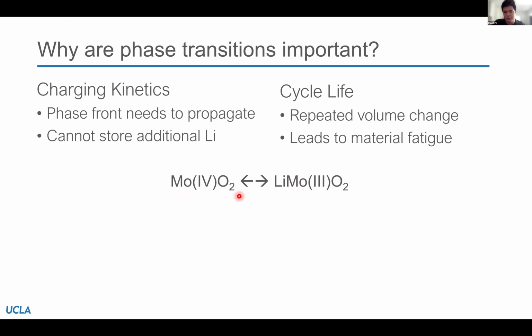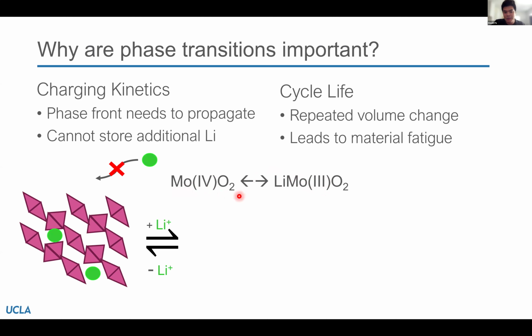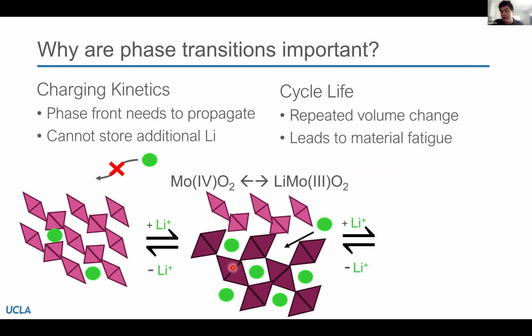If we look at this at a structural level, we have exactly that, empty MoO2, where we insert lithium. But now talking about phase transitions, at a certain point, you could think of it as a solubility limit of lithium in this structure. We're adding new elements to a crystal structure, so that creates strains. For most battery materials, you reach a point where your lithium concentration is too high and you can no longer incorporate additional lithium. In order to completely fill our structure and to continue charging or discharging, what needs to happen is what's known as a first order phase transition, in which we must nucleate and grow a new phase. So we're moving our atoms around in our crystal structure to be able to accommodate more lithium.